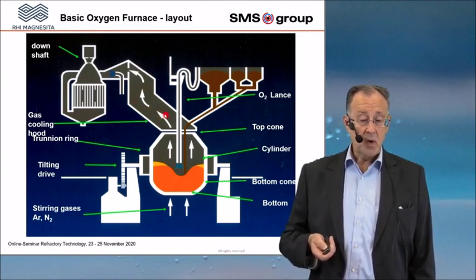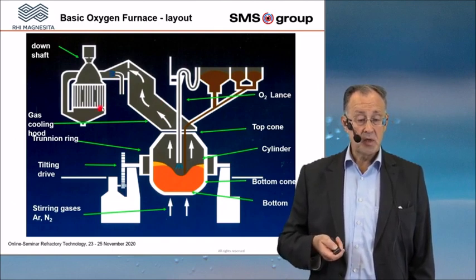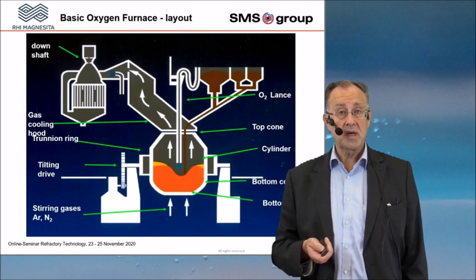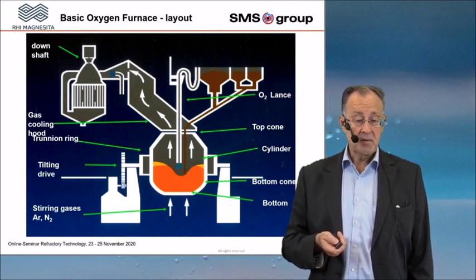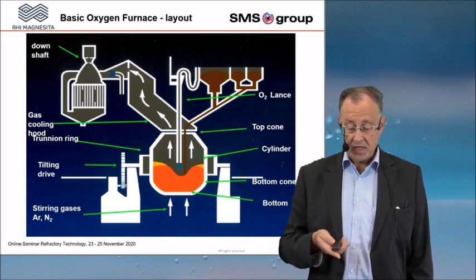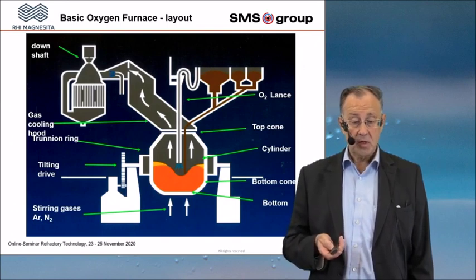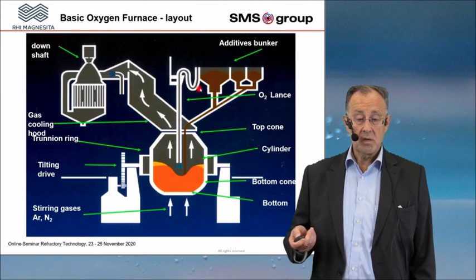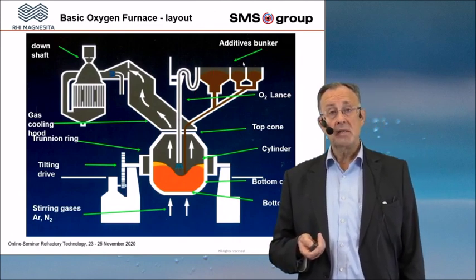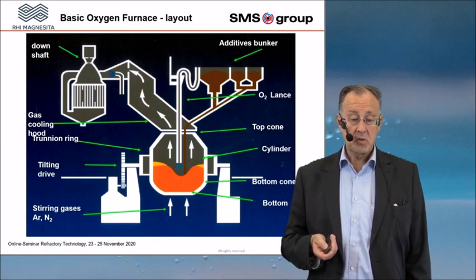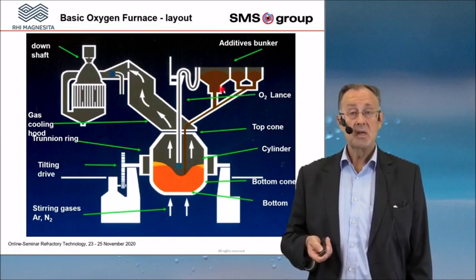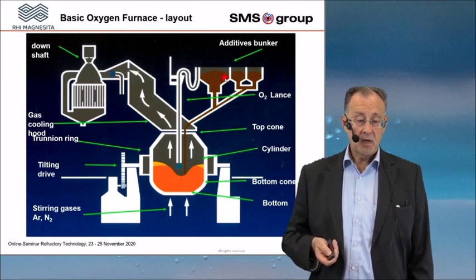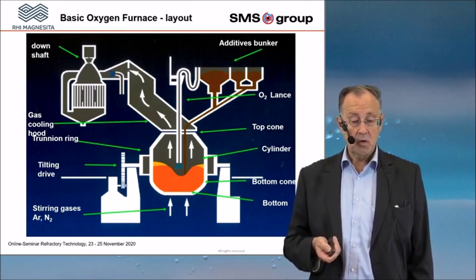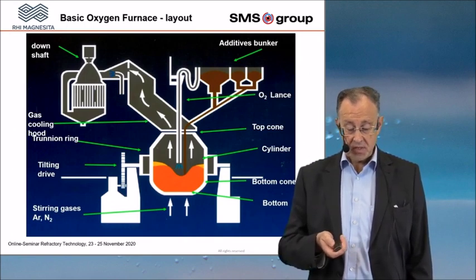You have a filter system behind that, so you can clean all the gases, because you have a lot of dust in your converter gas, so that you can achieve the requirements from the environmental side. Then you have a kind of ventilator to suck the gases out of the converter. And at last you have on top of the converter a bunker system. There you can put all your additives, so that you can feed this material during the blowing process, especially at the beginning of the blowing process, online or directly into your converter, and to support the activities inside the BOF vessel.